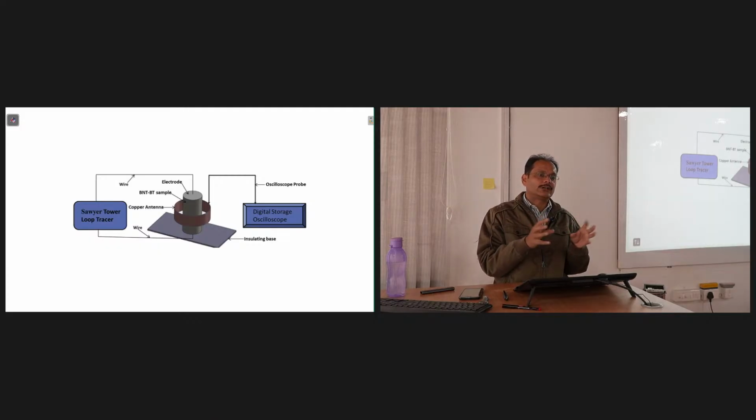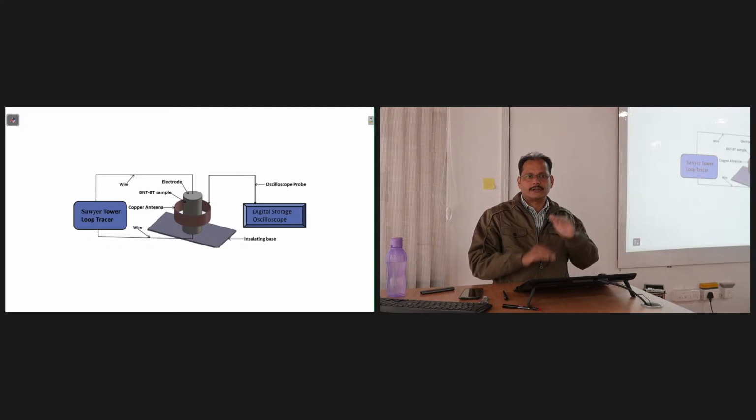The unit cell is not uniform; there is some deviation. So it is referred to as a non-centrosymmetric structure, because the symmetrical position at the center is lost. Some variation occurs: barium and oxygen, or titanium and oxygen atoms, are shifted.